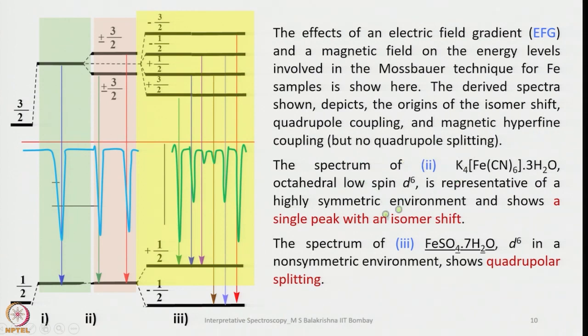The spectrum of K4[Fe(CN)6]·3H2O, octahedral, low spin and d6, because it is a plus 2 state. d6 is representative of a highly symmetric environment and shows a single peak with an isomer shift. It is a highly symmetric octahedral molecule. It shows a single peak with an isomer shift here. The spectrum of FeSO4·7H2O is also d6 but in a non-symmetrical environment. As a result, it shows quadrupolar splitting here. You can see quadrupolar splitting here.